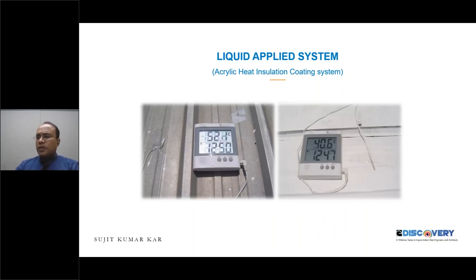These are real photographs I took during my previous companies, where I used to do demos of this particular coating. You can see the minimization of the temperature at 12:50 a.m. in the morning, where the non-coated area gives you a temperature of 62.1 degrees Celsius. After application of the coating, it gives you 40 degrees Celsius on the same surface, in the same area, at approximately the same time.